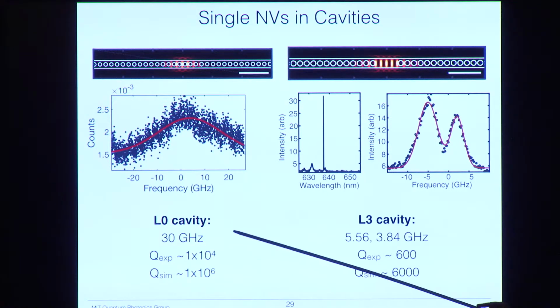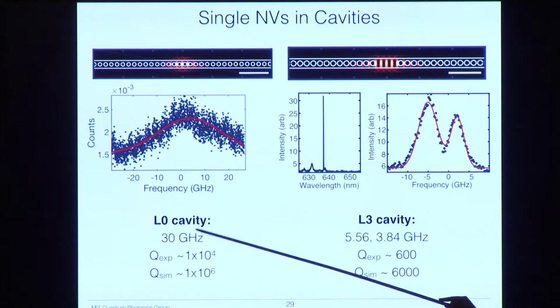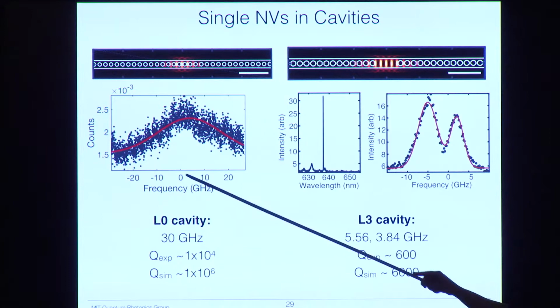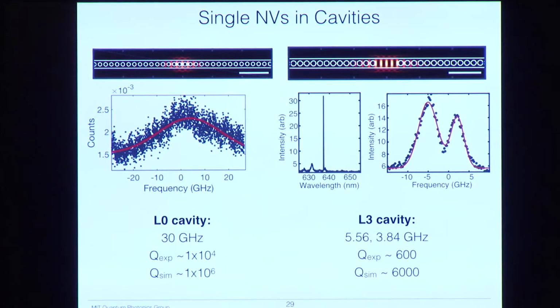And so when we look at NVs in what we call an L0 cavity, we see even broader line widths, so up to 30 gigahertz, tens of gigahertz. And so that is not good for quantum information processing. But when we look at L3 cavities, we see that we can recover the line widths from the waveguides. And that makes sense because here, an NV in an L3 cavity kind of looks like it's in a waveguide. It's around 100 nanometers from all surfaces.